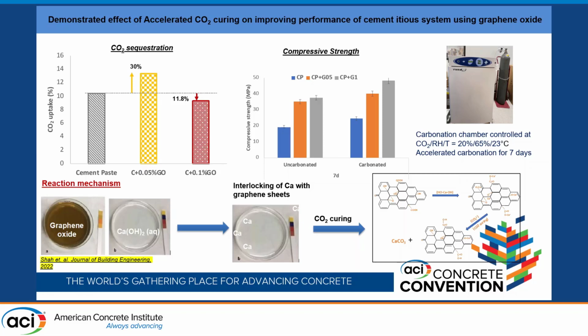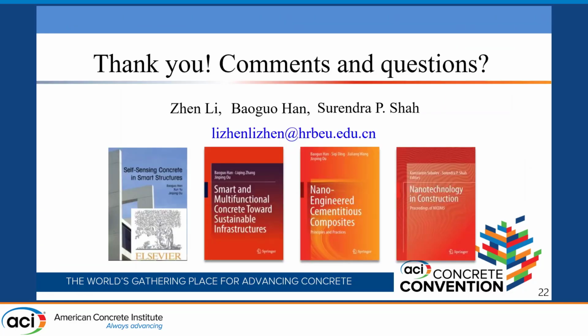And you can see the results of CO2 sequestration. There is a substantial increase, 30%, when you have, I think, what's the amount of GO here? 0.05% and 0.1%. And not only that, but the mechanical properties with addition of GO, for both uncarbonated and carbonated, are substantially increased. So it's very interesting how the observations we made at the nanoscale corroborated very well with the other properties. So I think that I will conclude with that.